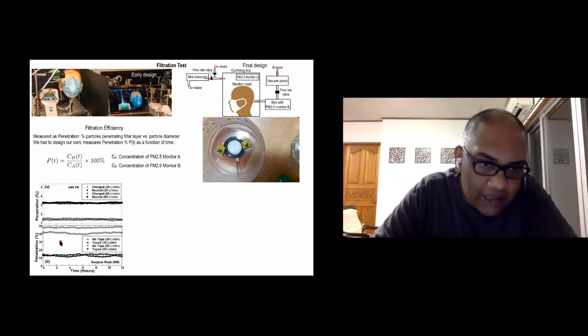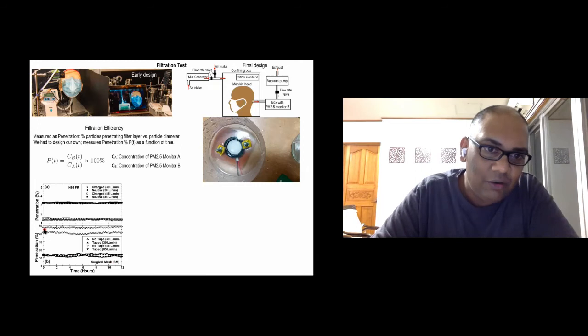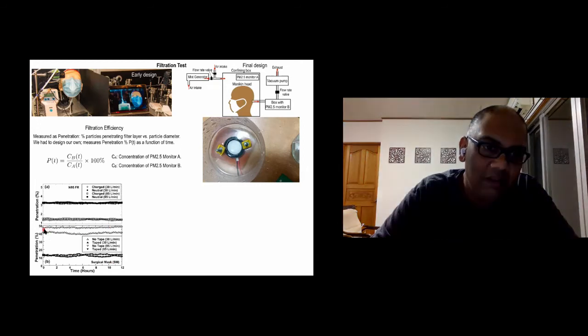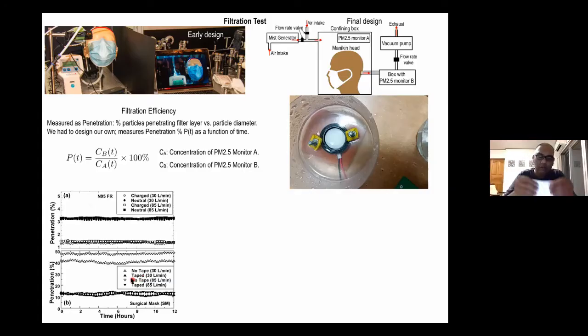Naturally, you can see that I was seeing close to 50% of particles passing through at 85 liters per minute. There were two types of tests. One was just the normal surgical mask as it is. The second was where I taped it to reduce the amount of interstitial gaps. When I reduced the interstitial gaps, the penetration fell to about 12% or so. That was very encouraging, but it was nowhere below 5% as one would want. So these are never going to be close to the N95 quality.